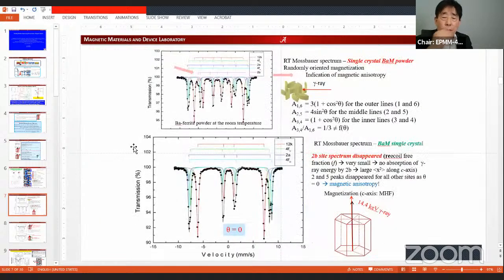This is the practically experimentally observed spectrum right here. This looks like a very small number of peaks, but that spectrum includes 30 because this is barium ferrite powder here. So we analyze this, and then we can get isomer shift, the saturation magnetic hyperfine field, and quadrupole splitting, and turn those parameters into magnetic properties.